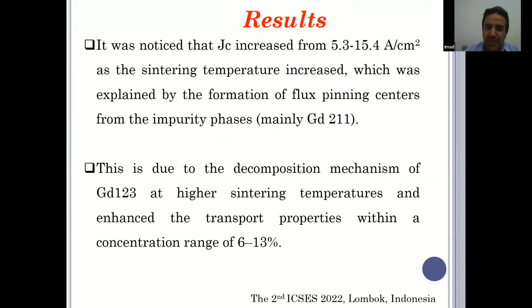So we tried to explain what is going on. Based on the increase in sintering temperature, we expect decomposition of the superconducting phase and formation of non-superconducting phases like the gadolinium 211 phase, which is orthorhombic and acts as flux pinning centers that enhance the critical current and critical current density. Based on the literature, impurities from 6 to 13% added to the pure superconducting phase enhance the critical current density by forming flux pinning centers.